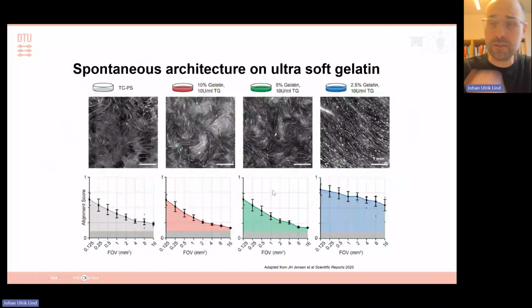But what we observed, and this was actually just a small bachelor project, was that if you go into sufficiently small, soft and viscoelastic substrates, then these domains increase in size. This is the same culture, but only if you go extremely deformable do you start to get a high degree of uniaxial alignment. This is obviously random, so we don't control it, but we can at least use this as a tool.